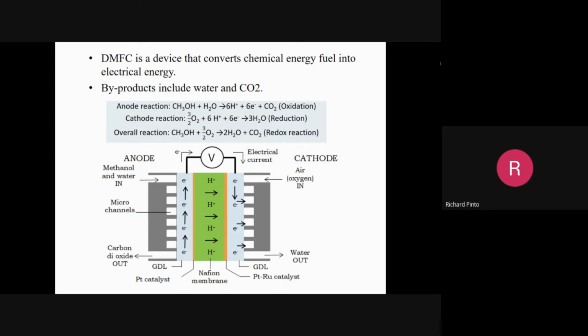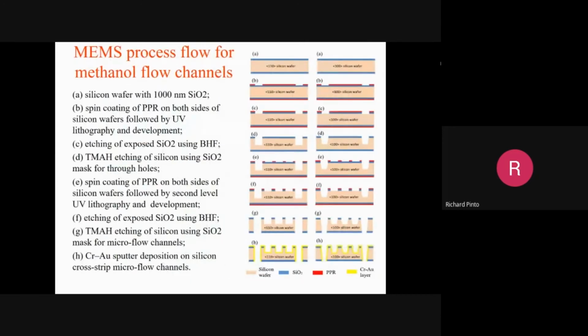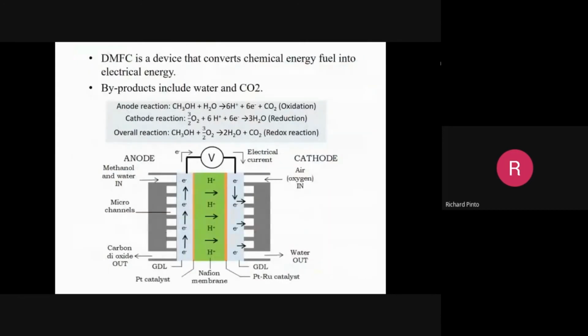And they flow through the GDL, called the gas diffusion layer, so that diffuses the liquid inside. And then there is a platinum catalyst. Actually, this platinum ruthenium catalyst is used on the left side because of breaking methanol; there's a mistake. So the platinum ruthenium catalyst should be on the left side, platinum catalyst on the right side. Platinum ruthenium is used for breaking methanol into carbon dioxide and H+. H+ goes into the Nafion membrane.